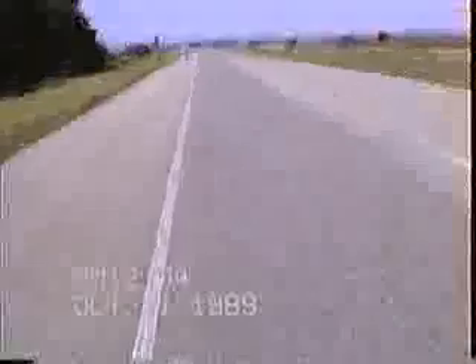Moving on up, going back up the test section, we see another transverse crack up here around station 2 plus 60. As before, you can see some cracking associated with the depression starting to begin on the lead side. This is what often happens: once this starts occurring, it just punches out almost, and that's why they've been having to patch, as well as to try to improve the rideability of this. The crack is more widely opened over there in the inner lane than it is here in the outside lane. It extends all the way across the pavement, including the shoulders.